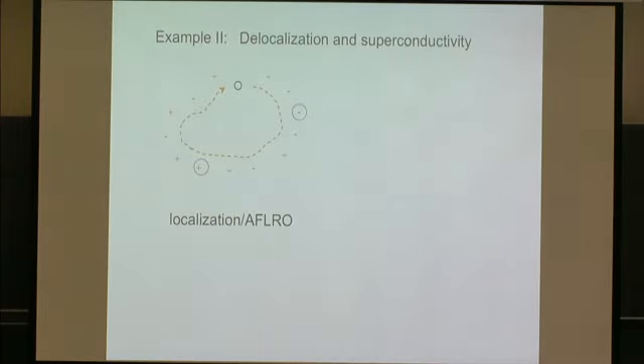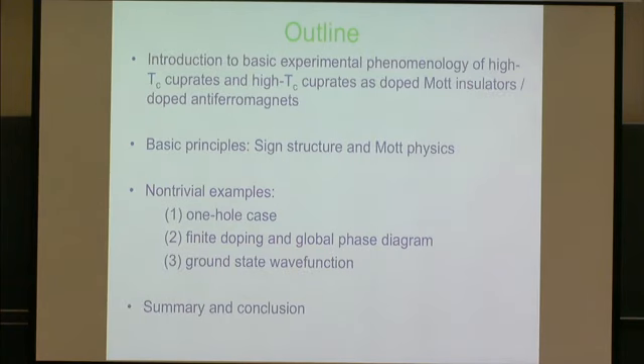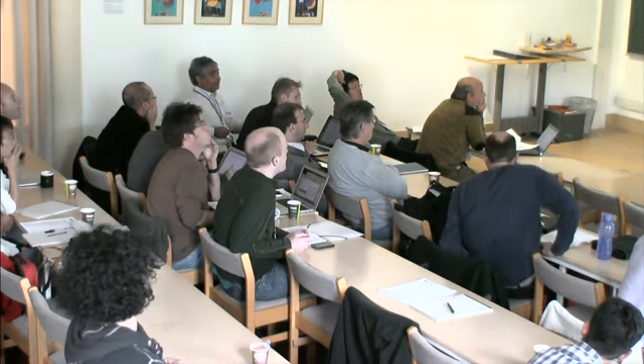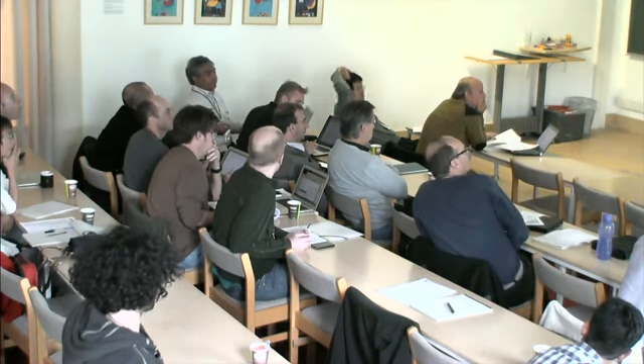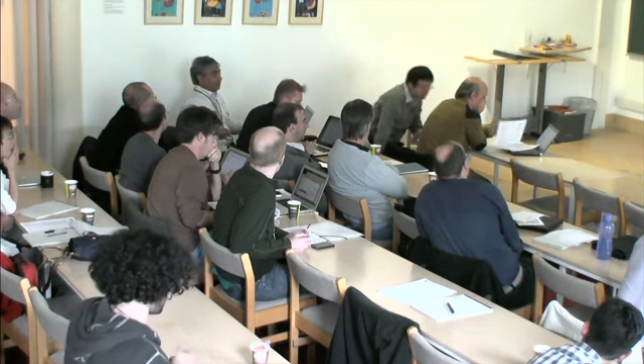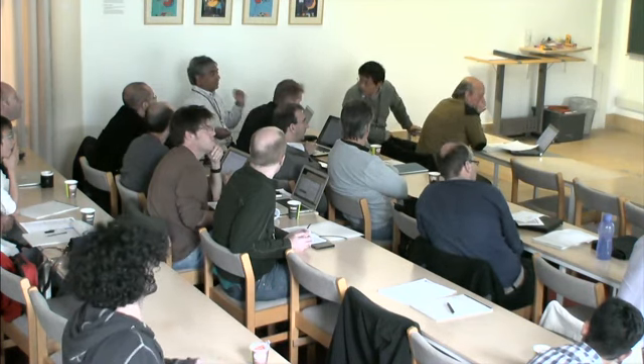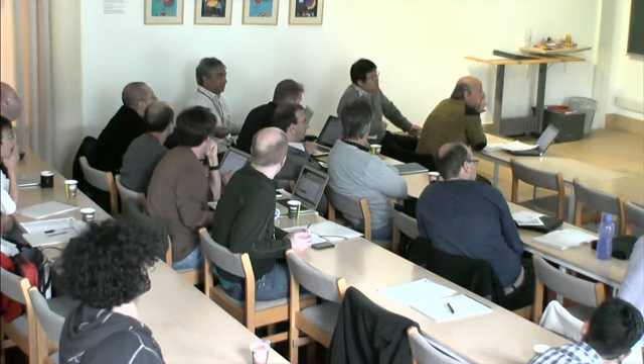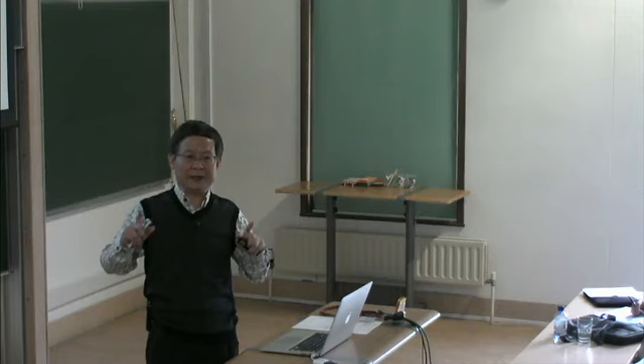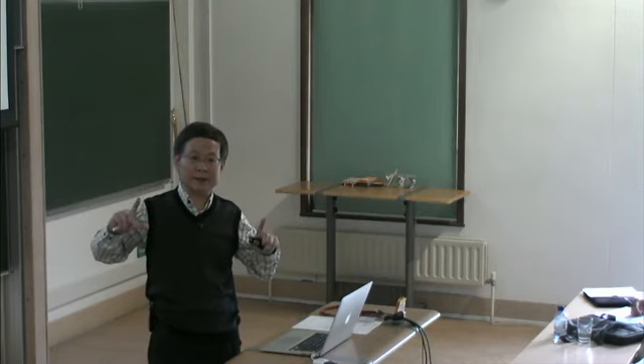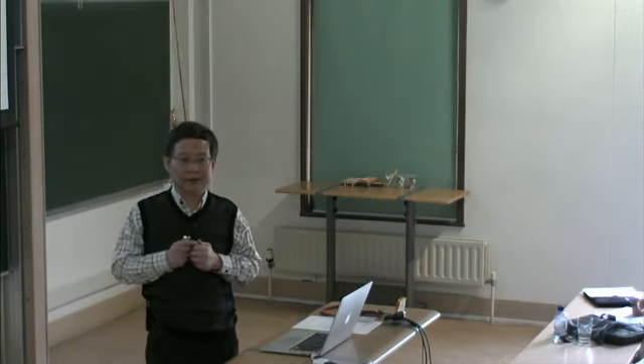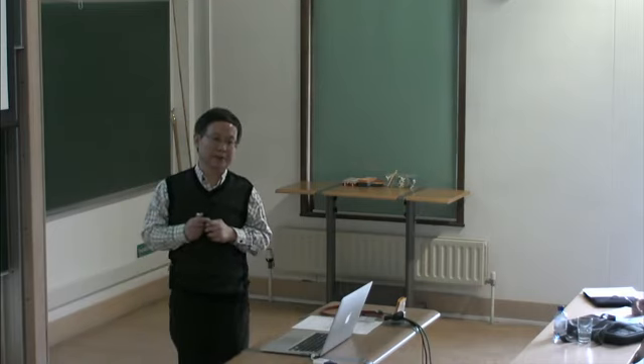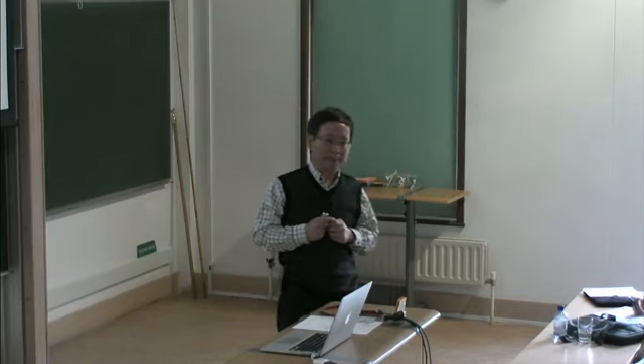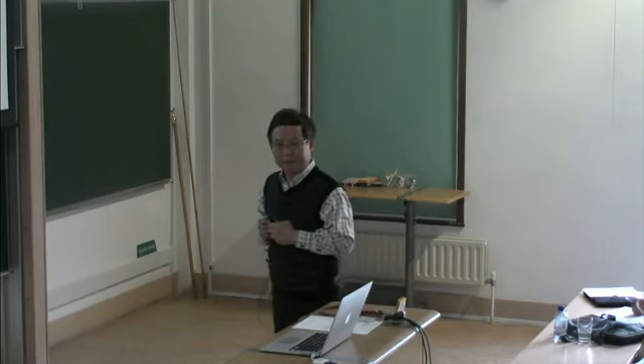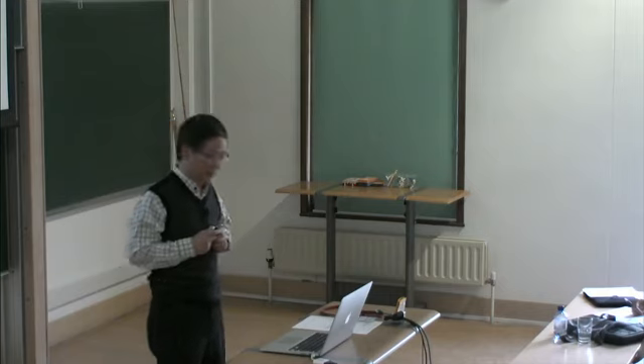Sorry, I have real trouble with that result. So you have an antiferromagnet with long-range order. I thought the general belief was that if you put in one hole, it is a quasi-particle with finite residue, with bandwidth about J over t. There's a lot of evidence to support that. But the evidence is based on small exact diagonalization. That's just too small. Perturbation theory and high-order spin wave expansion. That's right, a huge amount of work, large N expansion. They all support the idea that there is a well-defined quasi-particle when you have long-range antiferromagnetic order.